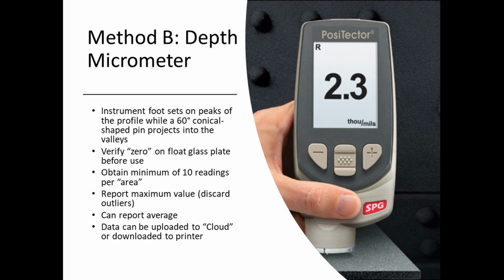Method B is called a depth micrometer. What we're doing here is actually taking pinpoint measurements of the surface profile. I don't know if you can see it from where you're sitting, but at the base of the gauge, there's a 60-degree cone-shaped point coming out of the bottom. The theory is it goes into the valley of the profile, the base of the instrument sits on the peaks. That depth or distance is reflected on the gauge in either mils or microns, whatever you prefer.